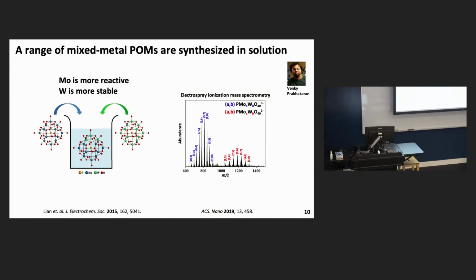So that was an interesting sort of fundamental observation, but we wanted to move beyond that and see what we could do in terms of doping of these atoms to improve their performance. The idea here is that pure molybdenum-containing clusters tend to be more reactive, while those that are tungsten-containing tend to be more stable. And we believe that if we found the right mixture of both atoms in these clusters, we should be able to optimize and balance those two competing concepts.